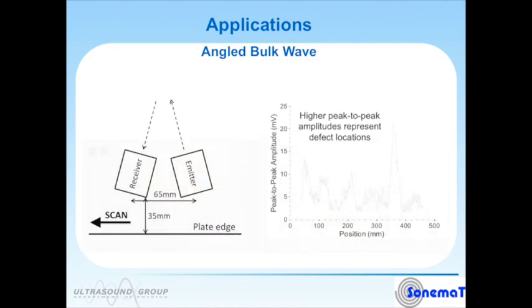The particular setup used was using an emitter and a receiver in a pitch catch geometry scanned along the weld from one side of the weld. And in each case, no matter which side of the weld the EMATs were positioned on or which face, front or back, defects were found in the weld with different levels of signal to noise, but all of the defects in this plate were found using this technique, and they couldn't all be found using conventional ultrasonic transducers.